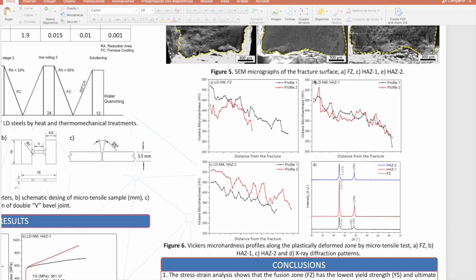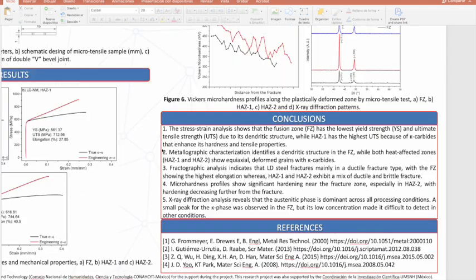Additionally, a small single peak is visible on the left side of the second main austenite peak, identified as the κ 200 carbide in the fusion zone. For heat-affected zone 1 and heat-affected zone 2, no evidence of κ-carbide is observed. There are variations in the height of each peak, which may correlate with the phase volume fraction in the study area. However, the diffraction intensity of each phase also largely depends on the orientation of the grains in each phase.